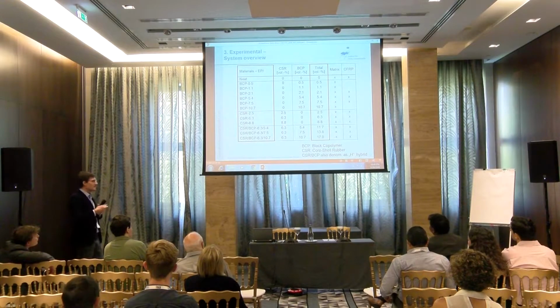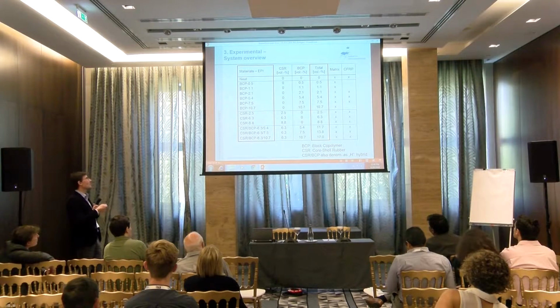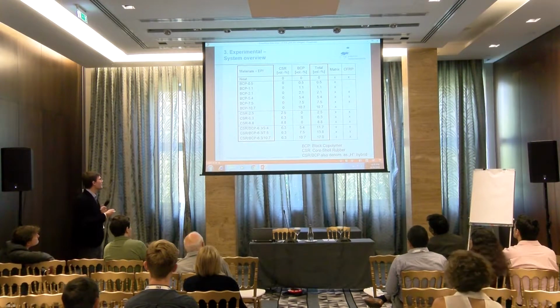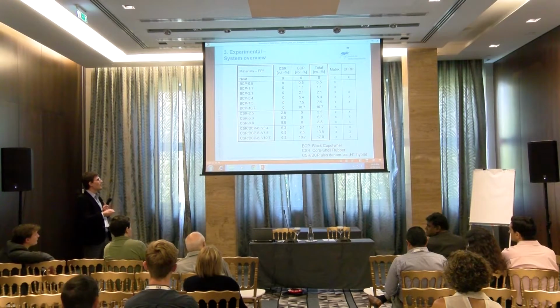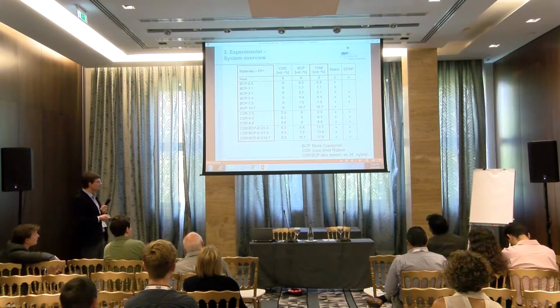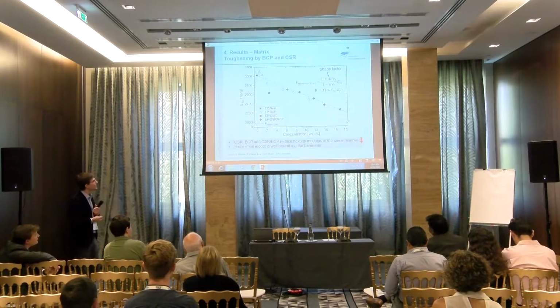We did different systems: a couple of block copolymer toughened systems, a couple of coarser rubber toughened systems, and a couple of hybrids. And the total amount of modifier was varied between 0.5 and 17 volume%. That will be important now, as you can see.